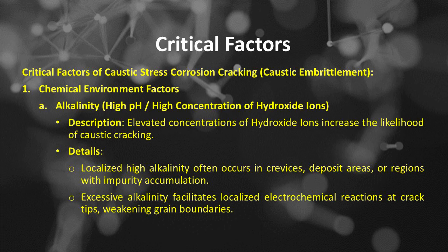Number 1 is chemical environment factors. Factor number A is alkalinity, or high pH, or high concentration of hydroxide ions. Elevated concentrations of hydroxide ions increase the likelihood of caustic cracking. Details of alkalinity: localized high alkalinity often occurs in crevices, deposit areas, or regions with impurity accumulation. Excessive alkalinity facilitates localized electrochemical reactions at crack tips, weakening grain boundaries.